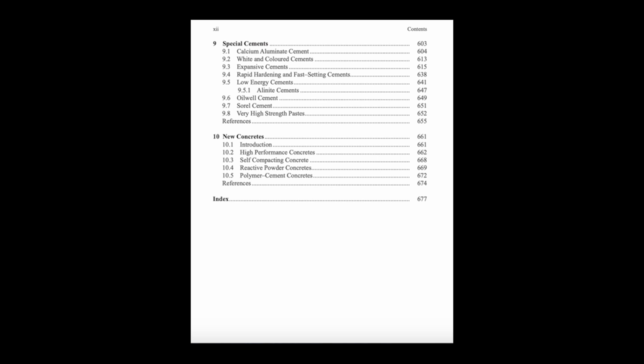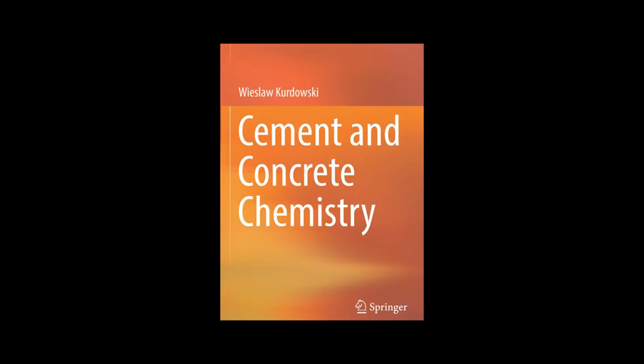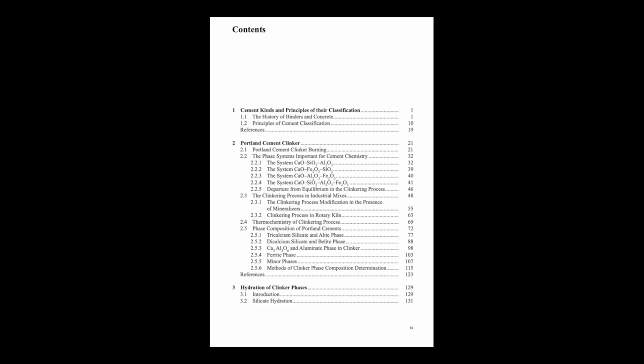Are there downsides? Yes, definitely. Excessive gypsum can cause problems later on, like expansion and potential deterioration of the concrete. How? It could be due to ettringite forming at later ages, after the paste has hardened. The growing ettringite crystals create expansive forces the hardened paste can't accommodate. Sometimes called delayed ettringite formation. Exactly, or internal sulfate attack, especially in cements high in tricalcium aluminate. Coarsely ground cement can make it worse, too, if large gypsum particles persist. So it's a delicate balance, enough to retard, but not too much to cause later problems?